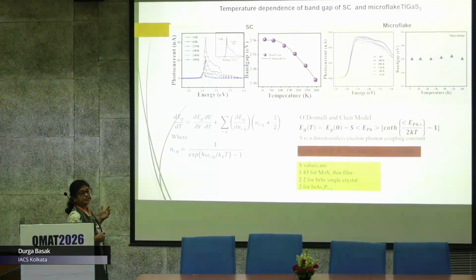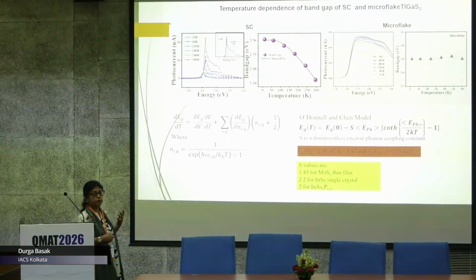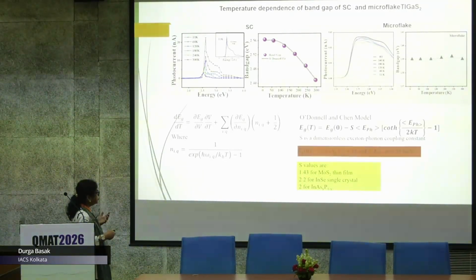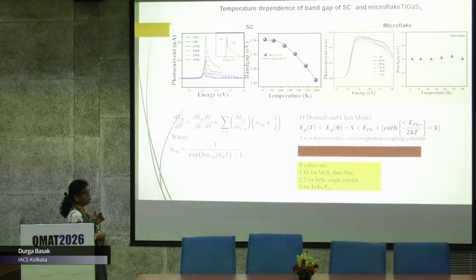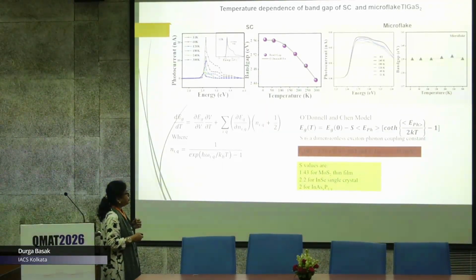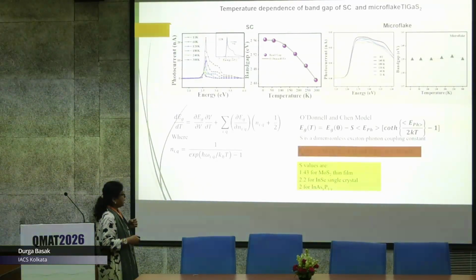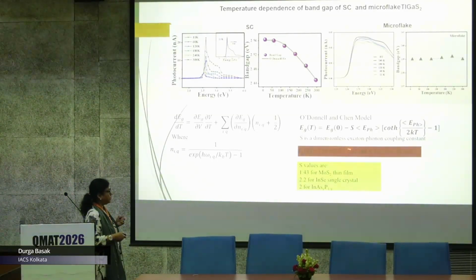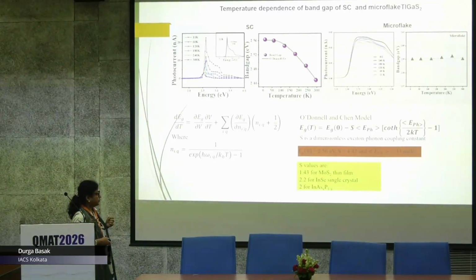So you know how band gap changes with temperature. When the temperature increases, the volume increases, of course, and this should give you a blue shift in the band gap. The first term is responsible for the blue shift, and this term with the phonon interaction should give you a red shift. This is the phonon occupancy following the Bose-Einstein distribution law. And this curve we have fitted with the O'Donnell and Chen model following this equation, and from there S, the dimensionless exciton-phonon coupling constant for this material, has been found to be 4.42. So you can compare with MoS2 and indium selenide, which are quite a lot lesser than this value.